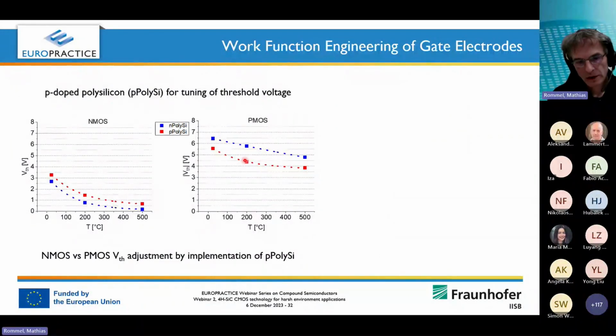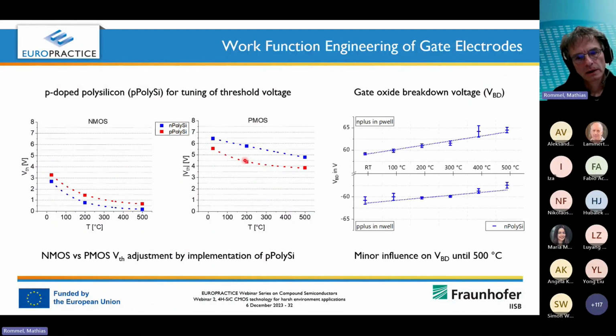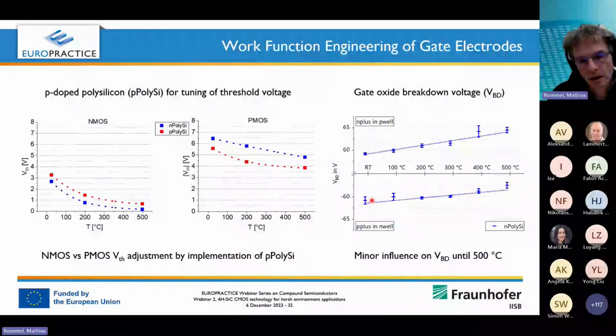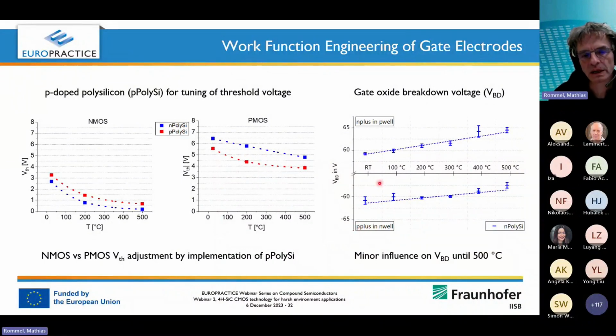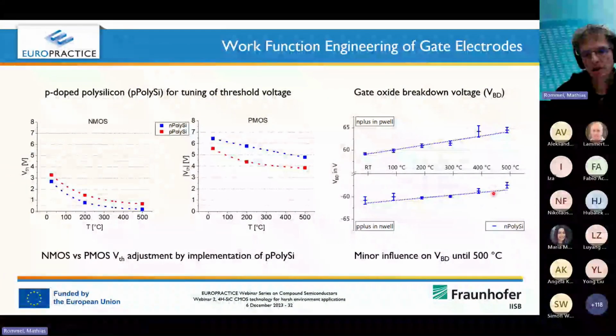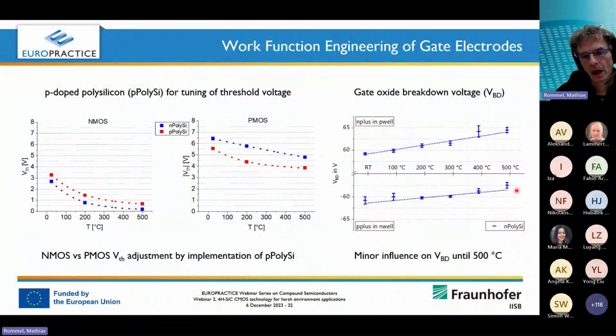Maybe in this context, I can also show the breakdown voltages of the oxides we use. So as you can see, we start again with the N-type polysilicon. It's around 60 volts for both transistors, or for both MOS structures, like polysilicon on oxide on silicon carbide, in this case highly p-doped, and here highly n-doped. Both show very similar behavior, and a relatively small influence on the breakdown voltages for the different temperatures.